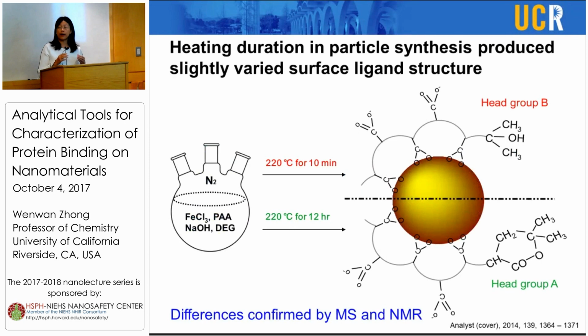However, these two batches of particles went through different heating procedures. One went through a very long hydrothermal process, longer than around 12 hours, and the other went through a very short heating process that lasts only 10 minutes. These two heating processes actually generate two kinds of ligand on the iron oxide surface.